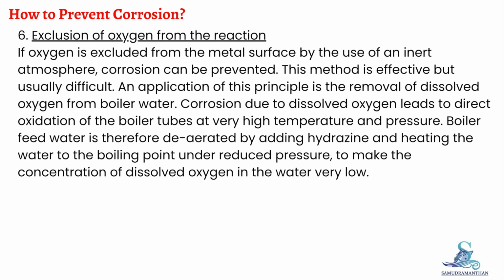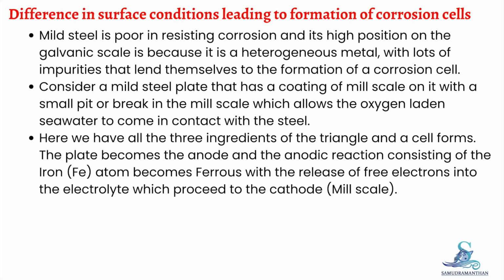Similarly, excluding oxygen from the reaction prevents corrosion. This is usually difficult, but one important application is in boiler systems. Corrosion caused by dissolved oxygen leads to oxidation of boiler tubes at high temperatures and pressures. Boiler feed water is therefore de-aerated, often by heating and by adding hydrazine to reduce the oxygen content to a very low level. Now let us understand how surface condition plays a role in corrosion.